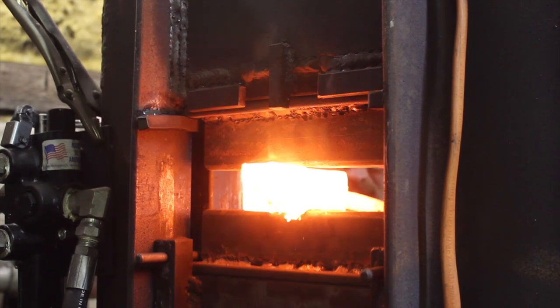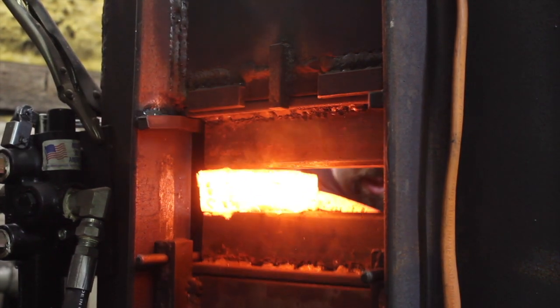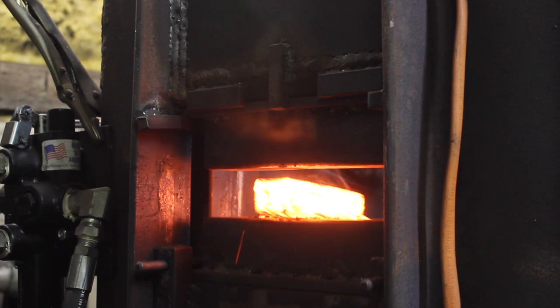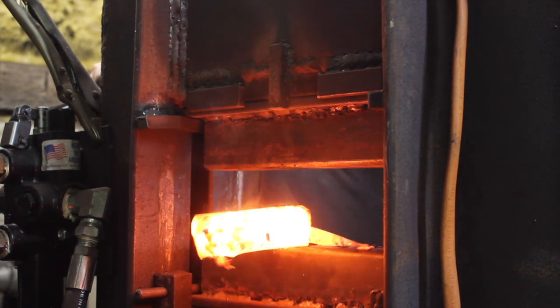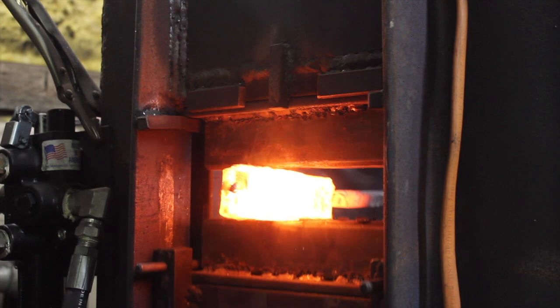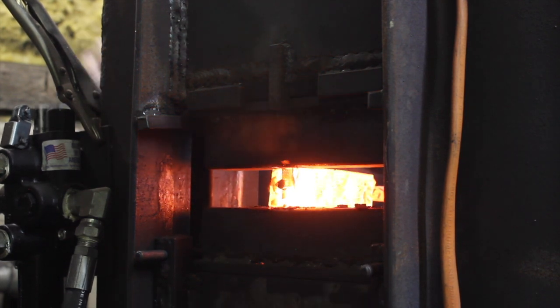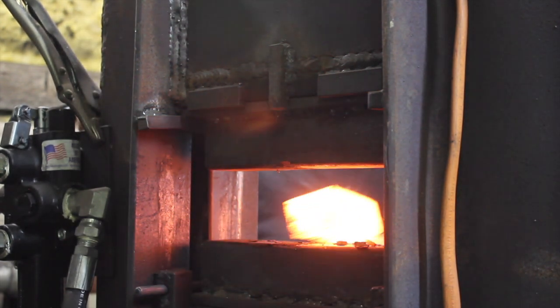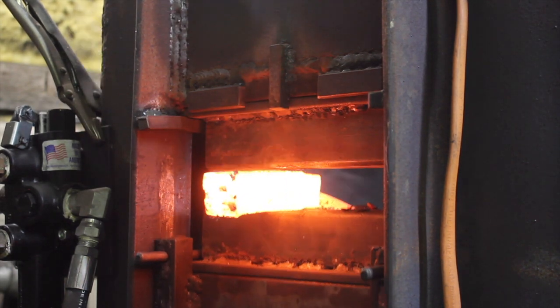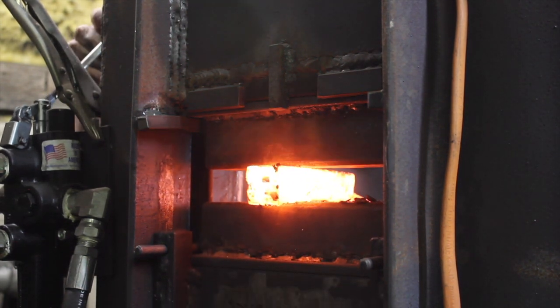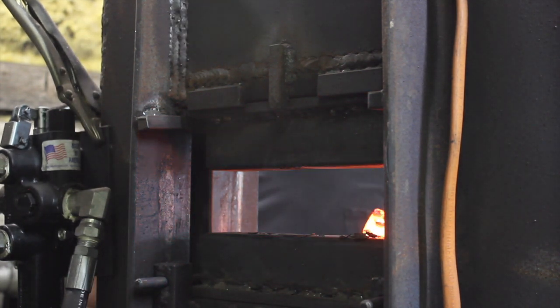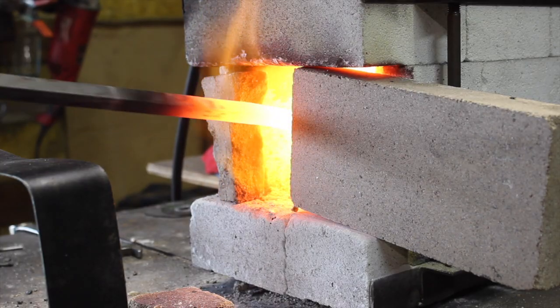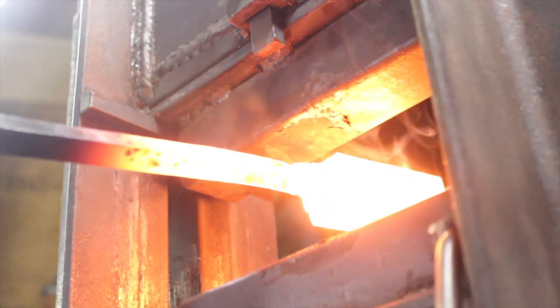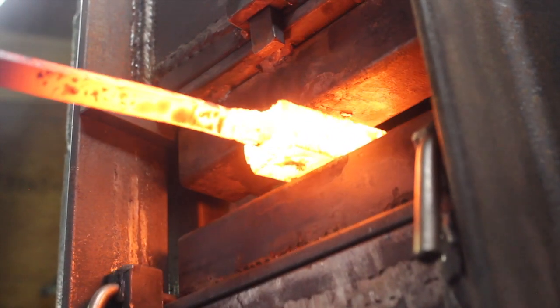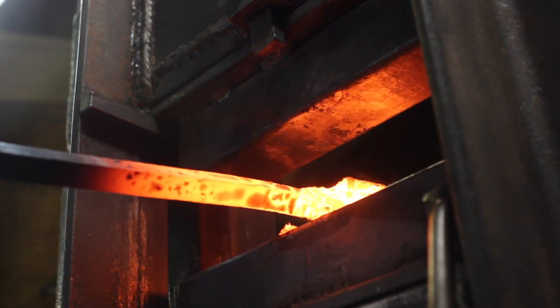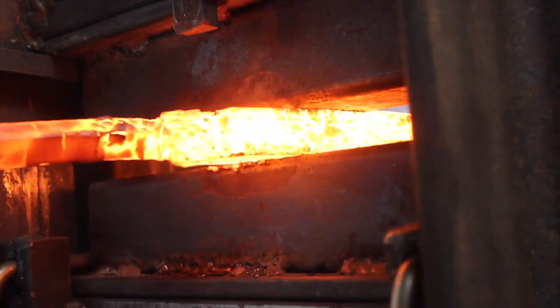And this is our second forge weld in the press. Sure is nice to have that machine. It's a blessing. I wouldn't be able to make Damascus blades and sell them at any kind of reasonable price and time frame if I didn't have that. So just making sure that everything is forge welded together, and then drawing the billet out again. And I do a 3rd forge weld on it to get up to between 200 and 240 layers, depending on, again, how many were ground off during the cleaning process.